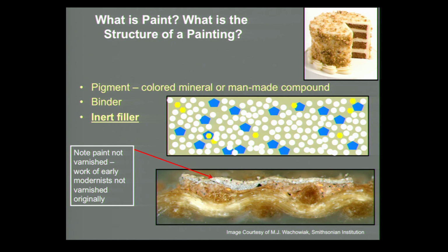There's actually 3 paint layers here, this kind of peach one at the bottom, then the gray one, and then a third pinkish one at the top. And you can see that most of the paint is actually made up of that white inert filler. And you can also see the weave of the canvas here, although typically we don't take a sample of the canvas. I also wanted to point out here that this painting is not varnished, and that's very characteristic of the work of the post-impressionists and the early modernists.